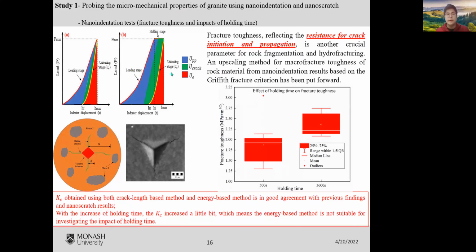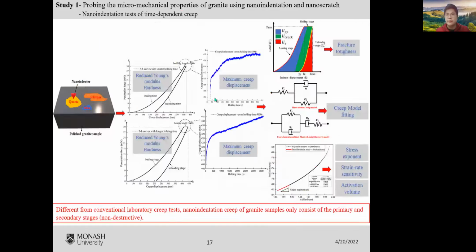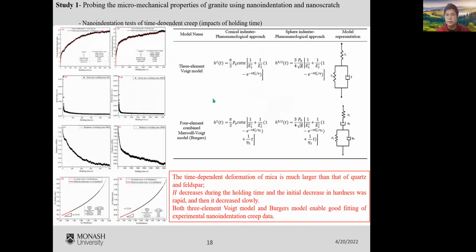Then we carry out nano-indentation to obtain the fracture toughness and also the time-dependent creep of our sample. And we use two different models, that is a 3-element Voigt model as well as the Burgers model, to fit our nano-indentation creep results.